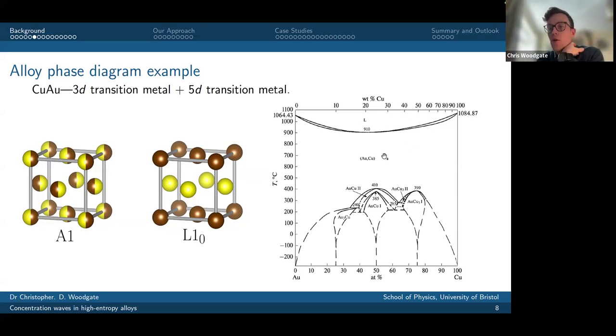And then what you can do is you can freeze in the equilibrium state at high temperature. And as you say, I've cooled the system down enough that my vacancies are essentially frozen, and I've frozen in that solid solution phase. And that's quite a common processing technique. Yeah. Okay, very good. Thank you. So absolutely, yeah.